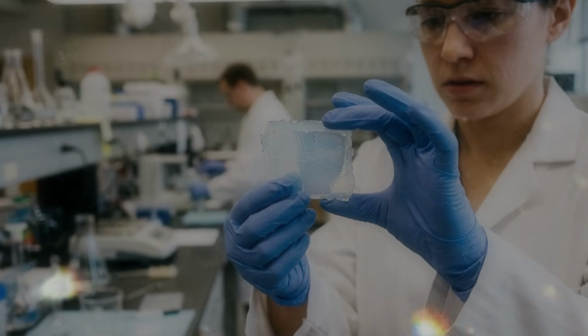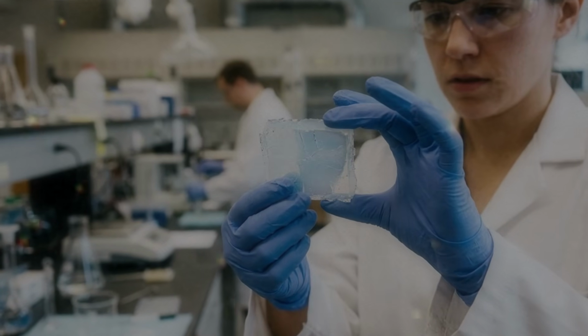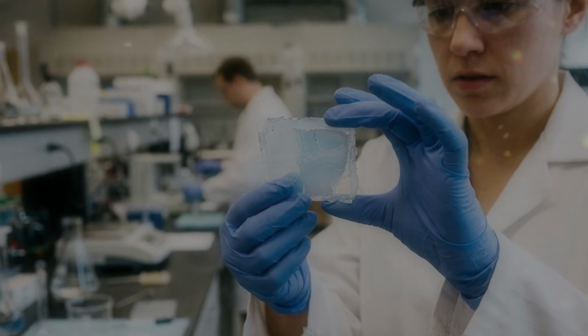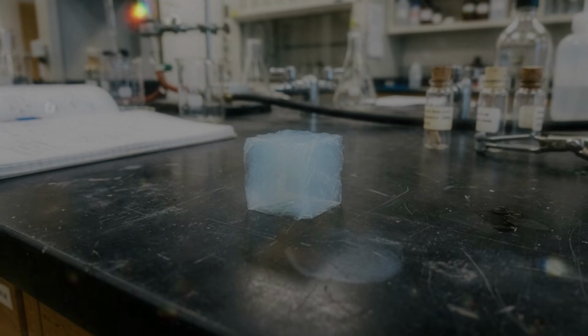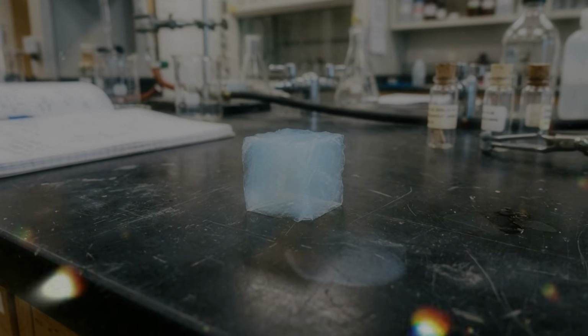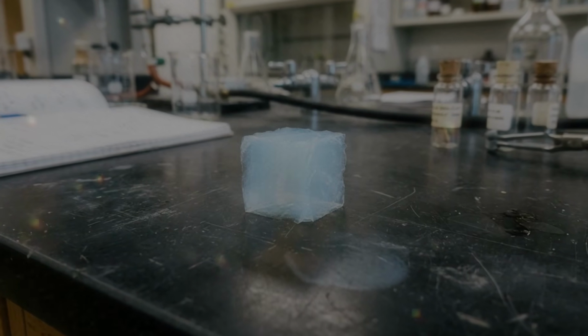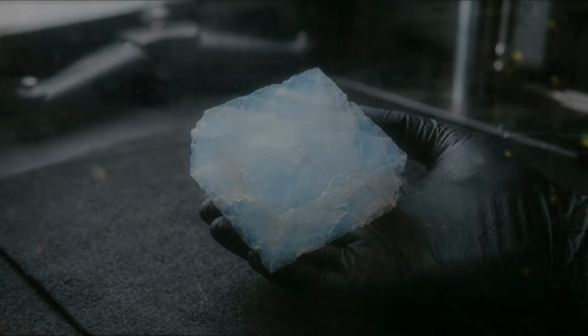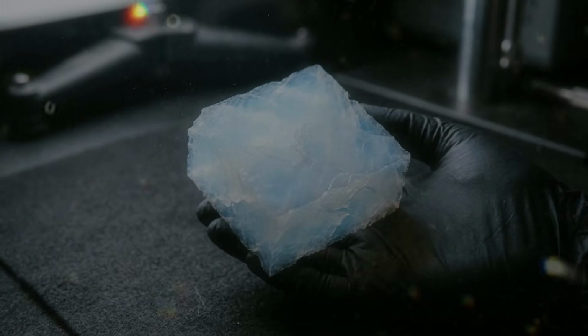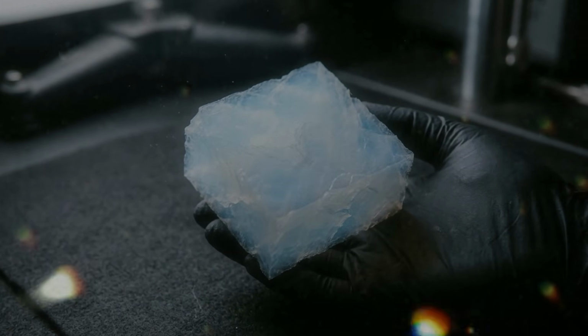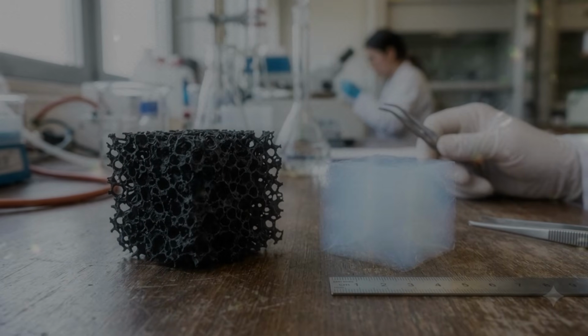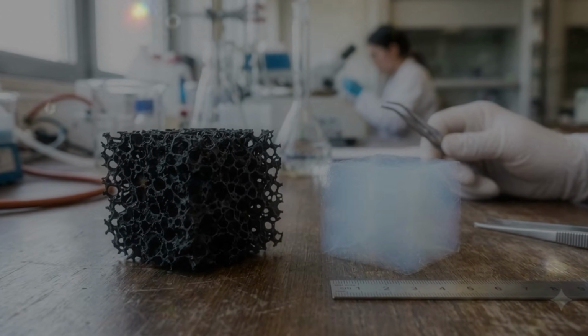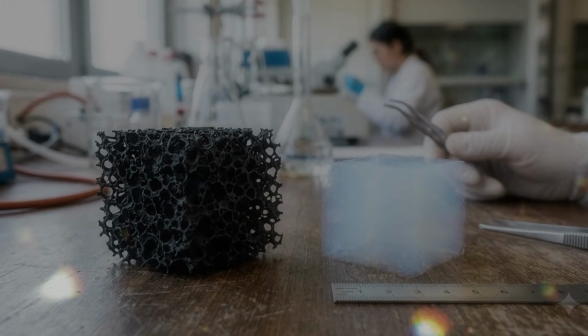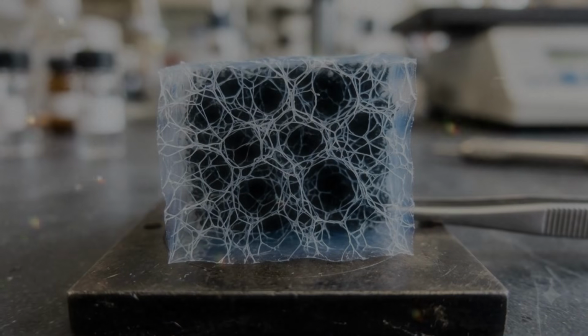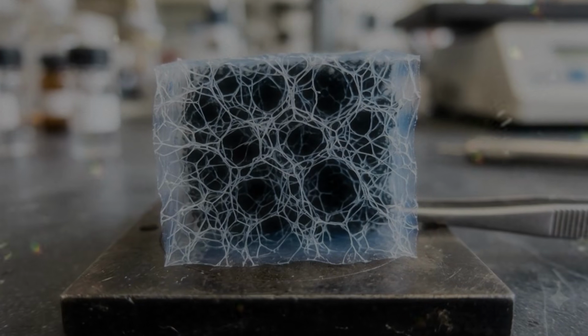As the sheets lose some of their oxygen groups, they become less comfortable remaining separately suspended in water. They begin approaching one another, folding, overlapping, and forming contacts. If the process is controlled well, they do not simply collapse into a dense lump. Instead, they create an open gel. Water remains trapped within the spaces between the connected sheets. The container now holds a graphene-based hydrogel, with hydro referring to the water inside it.